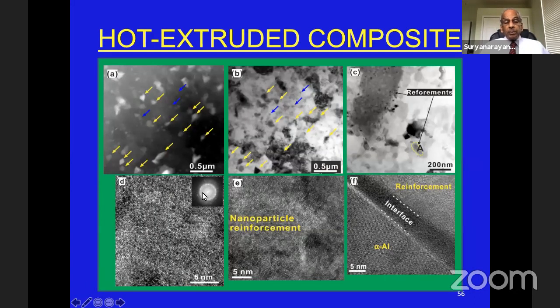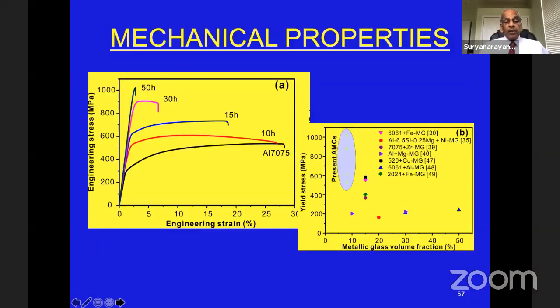But if you look at the TEM pictures, you would notice that there are all these metallic glass particles all around, and these with blue arrows represent the magnesium silicide, because this is hot extruded at a relatively high temperature, and therefore the magnesium silicide also has precipitated out along with the metallic glass particle. But the important point here is this nanoparticle reinforcement. You can see it is still amorphous. So they have a reinforcement. This is the alpha aluminum matrix, and the interface is there because of the small reaction that took place between the aluminum and the reinforcement.